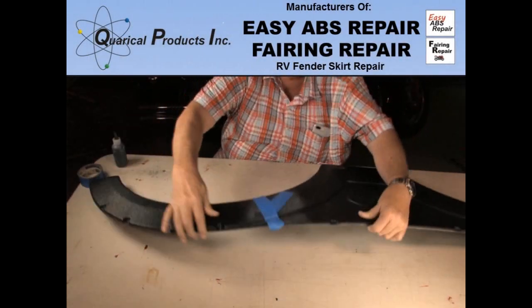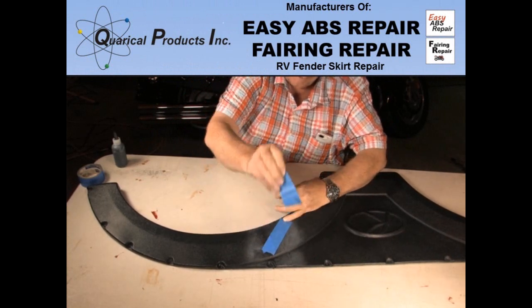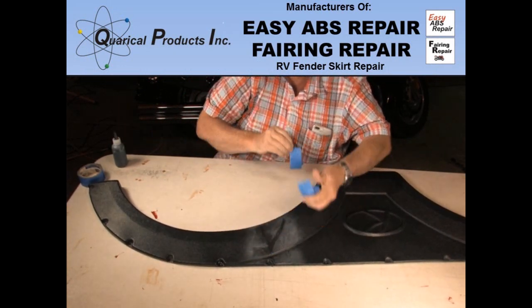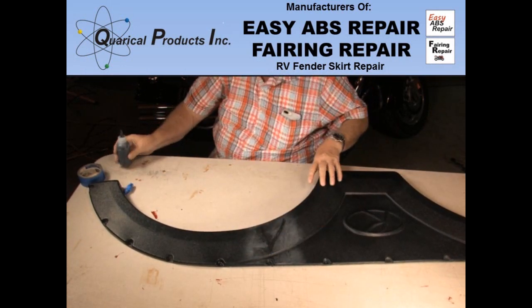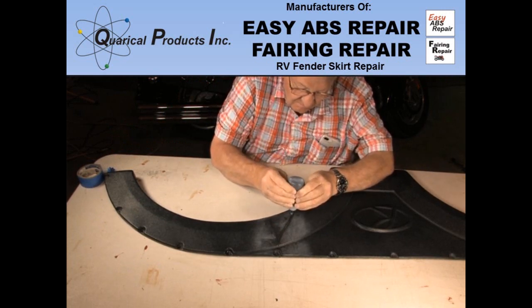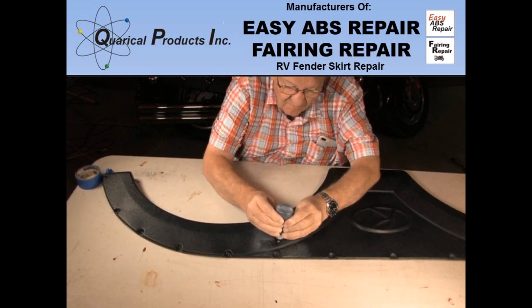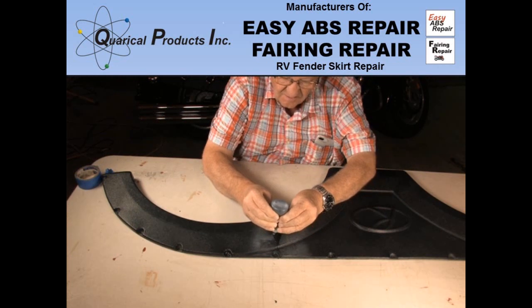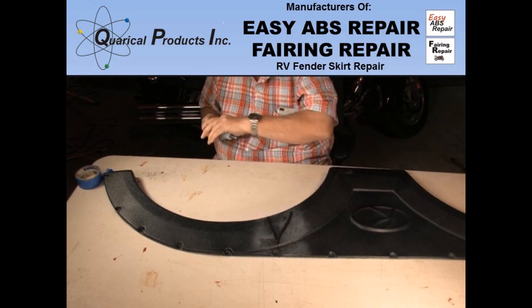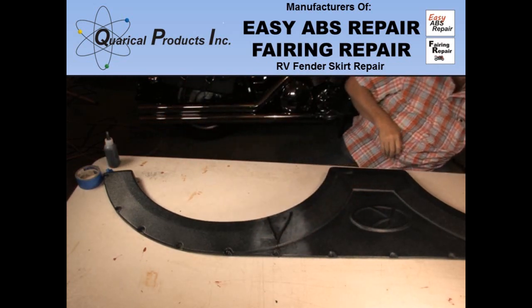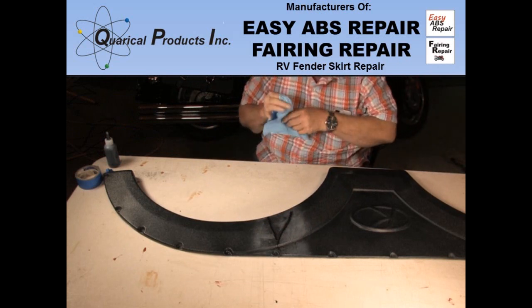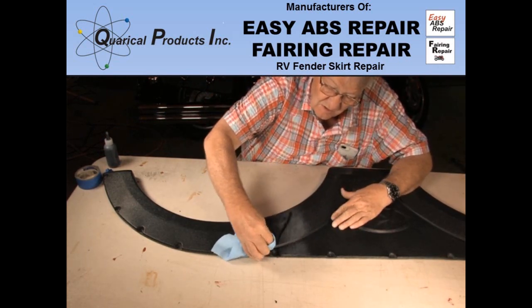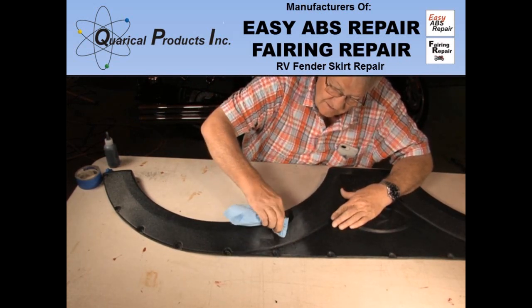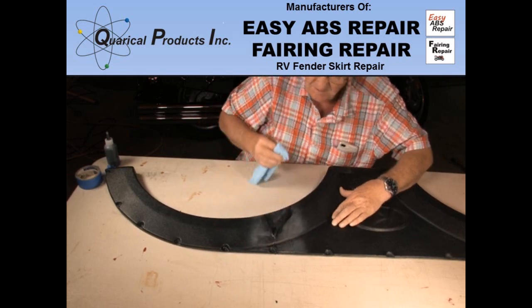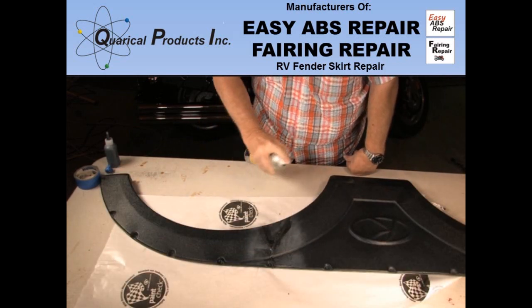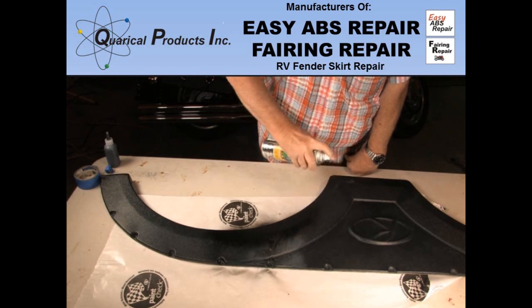Later, the resin is cured and the fender skirt is back to being a structural unit. I take the tape off and flex the skirt and it is good to go. Unfortunately, there was so much silicone and duct tape adhesive that the cleaning process dulled the surface. I applied a small amount of resin over the cracks and using a lint-free rag, rubbed it into the surface. The surface of this vinyl has a wrinkle finish and is hard to match to. I then give the skirt a coat of black paint.